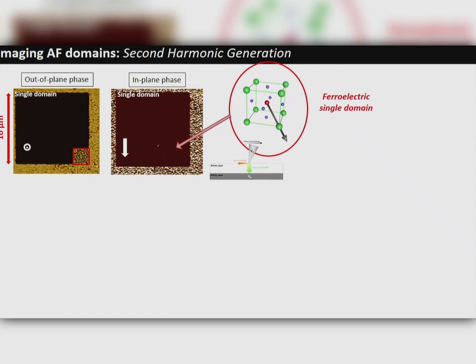So we enter the game, but as you have seen at the beginning, the electric structure is quite small, and as we are using an optical technique, we are limited by the diffraction. So the first thing we wanted to do is to increase it, and to do that in a single ferroelectric domain. And this is possible, as I already mentioned, if you use this PFM and then you apply a voltage, you are able to write large single ferroelectric domains. So basically, here, already for the problem I mentioned at the beginning, how can we control all the multitude of antiferromagnetic domains, the multiple T domain, multiple S domain. Here, you already reduce the possibility of T domains from 12 to 1, basically.